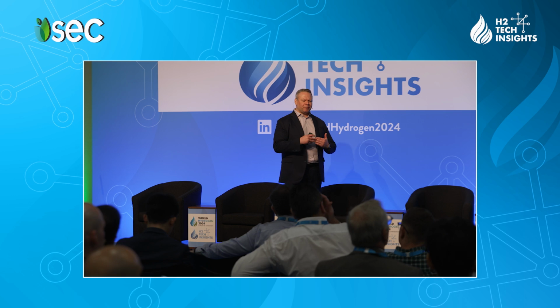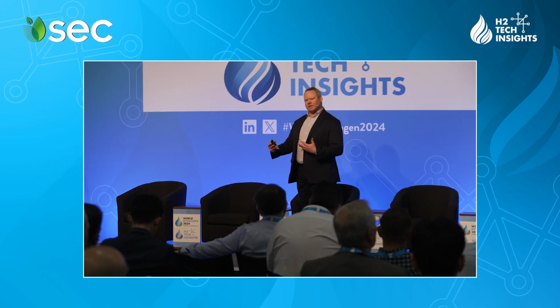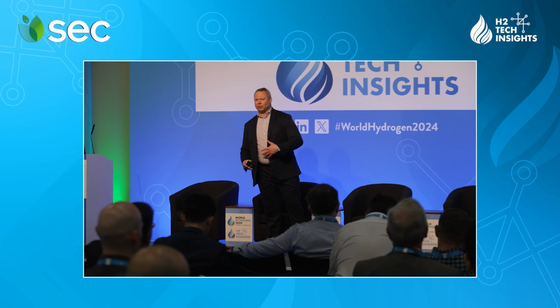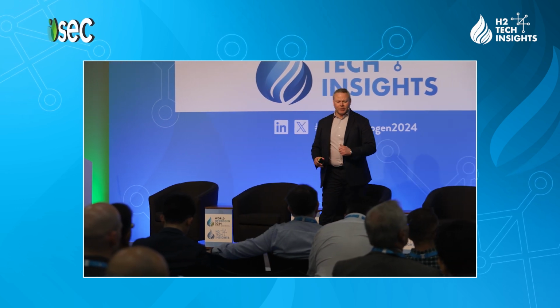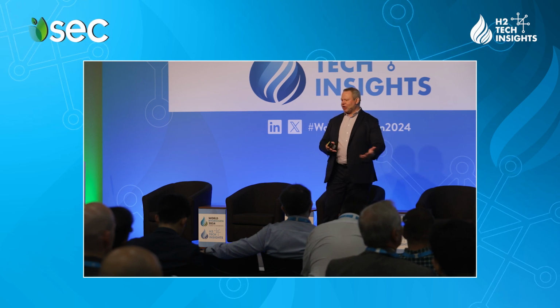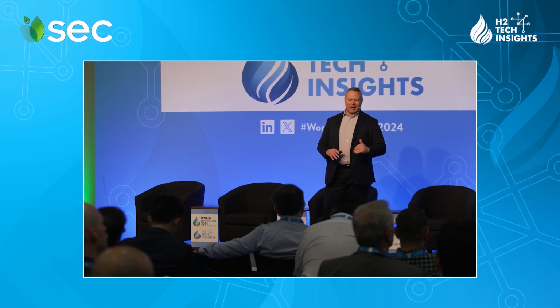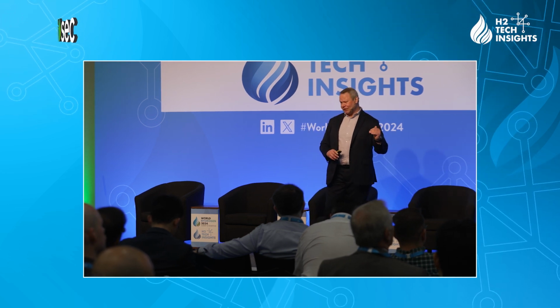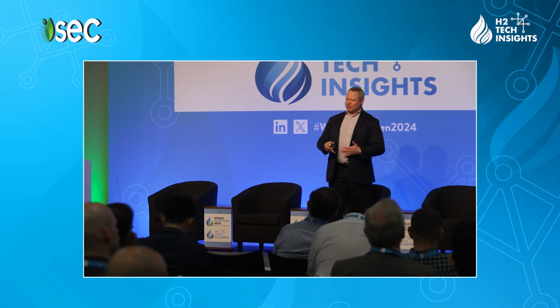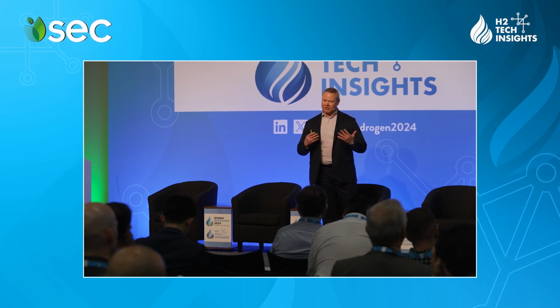We see that typically when you drop from 0.4 to 0.1, you see this categorical difference in the behavior of sintered PTLs, which is what Mott makes, and fiber PTLs, which are made by other companies in the world. When dropping from 0.4 to 0.1, the sintered PTL has a small change in the cell efficiency at 3 amps per centimeter squared, but the fiber PTL has an extremely large change in its efficiency, and that has to do with the geometric effect. Simply, there is more contact to the anode, which is the most precious thing you can have in a low-loaded electrolysis cell, in the case of the sintered PTL.